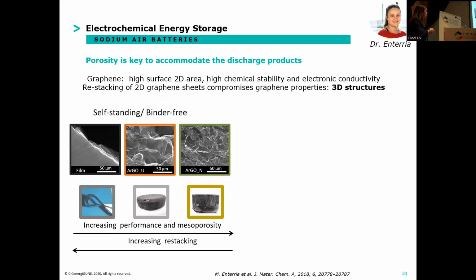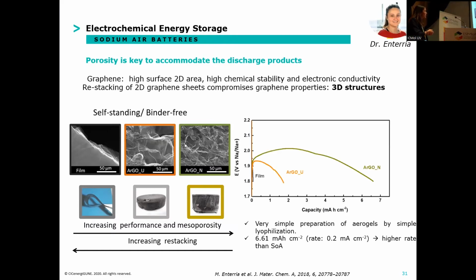Then we were increasing the mesoporosity by different freeze drying temperatures. And we have seen that in this case, increasing the mesoporosity, we increase the performance. Here we have the discharge, and we can see that the higher the mesoporosity, the higher the discharge capacity. So for these batteries, the porosity and the mesoporosity is very important.